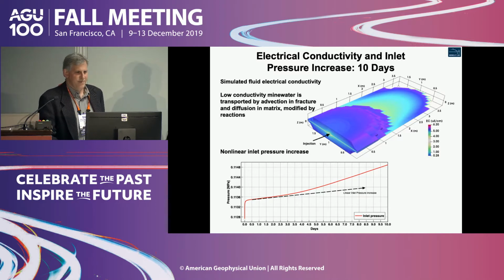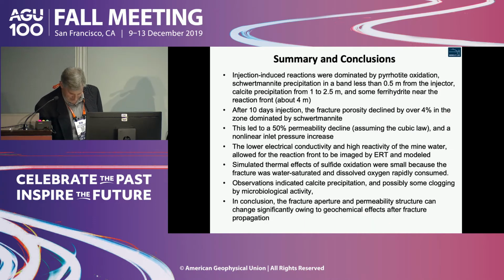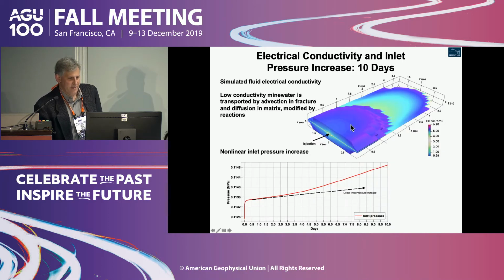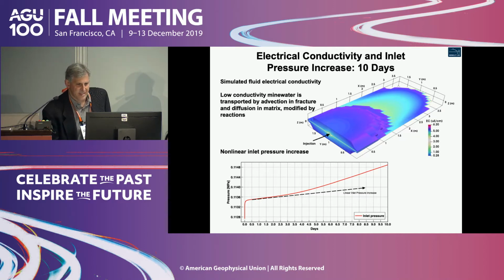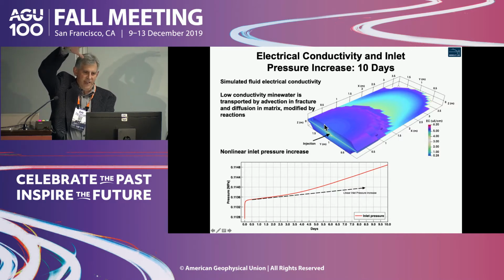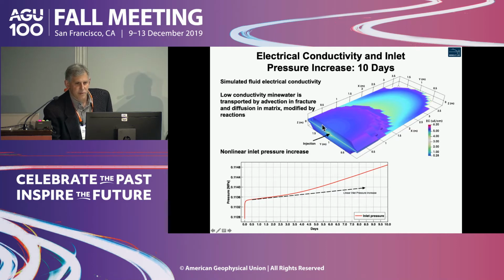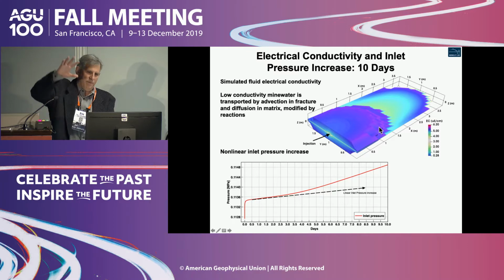Two more slides. So then we looked at the electrical conductivity, which is a really good way of looking at how the fluid reactions are moving through the system. So we're injecting. The electrical conductivity of the injection fluid is lower because of the lower salinity, also because of the lower temperature. But you can also see it's diffusing into the rock matrix. And the rock matrix is reacting. It's starting to get this reaction front moving into the system. And then you have the front that's moving down the fracture. So out here, it's pretty much just confined to the fracture, but out here, it's already migrated in.